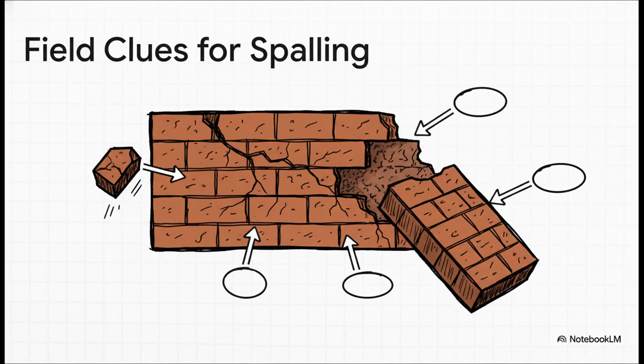Now, when our detectives show up at the scene, the evidence for this kind of attack, which we call spalling, is usually pretty obvious. They'll find telltale clues everywhere. Big visible cracks, chunks of material that have just broken off, or even entire layers that have peeled away from the wall. It's a clear case of structural failure.